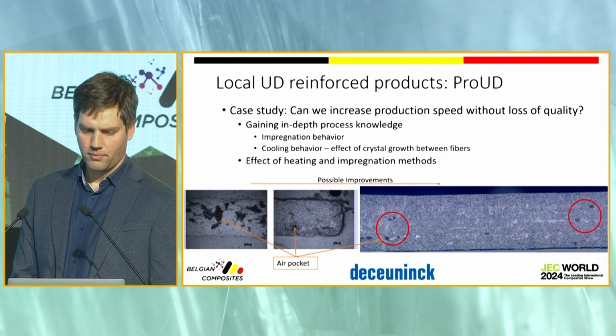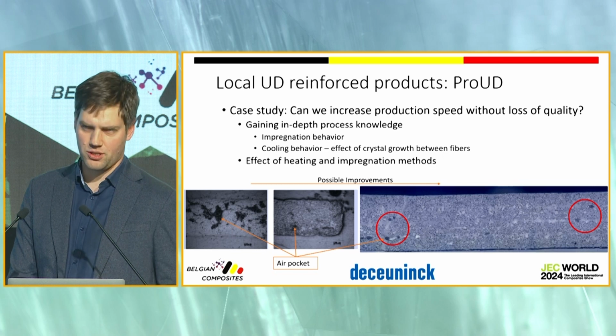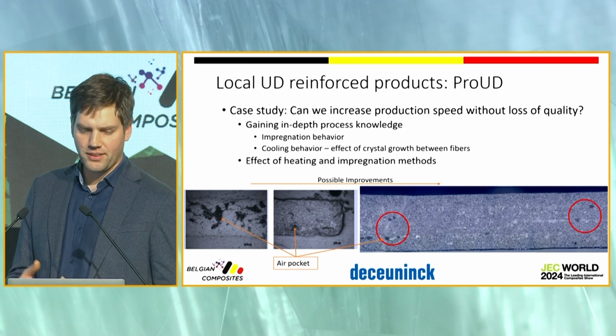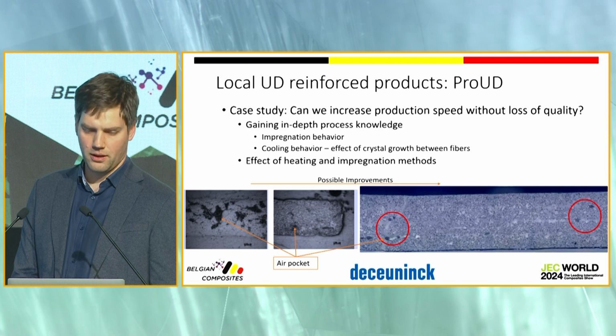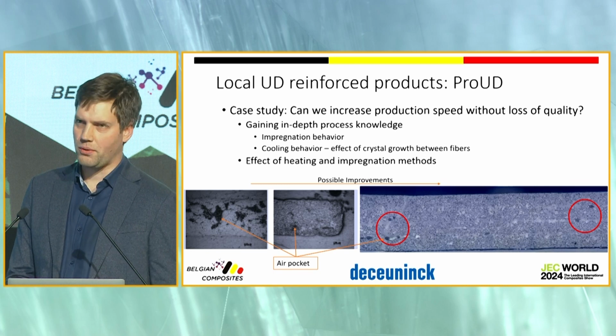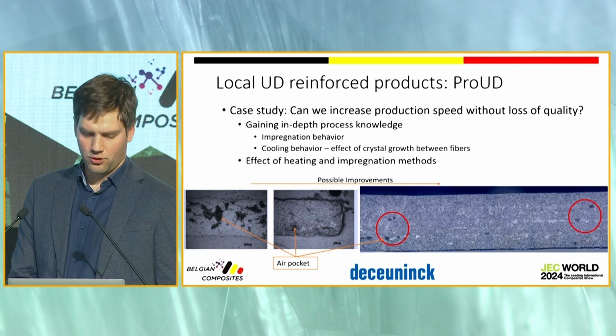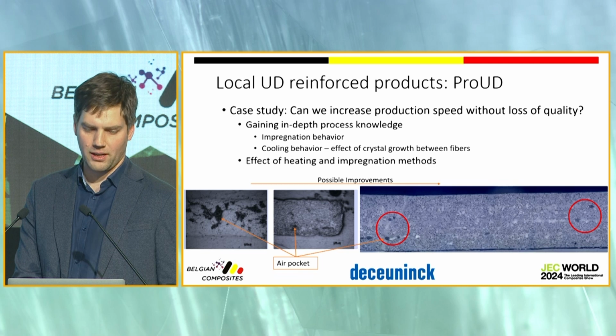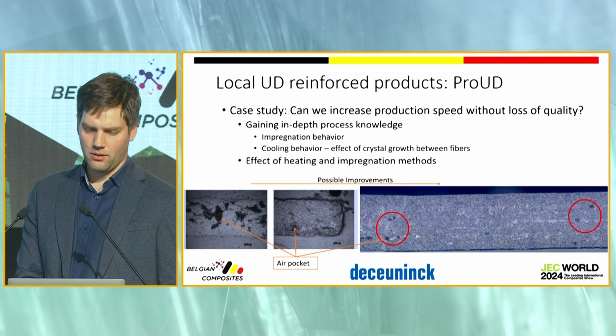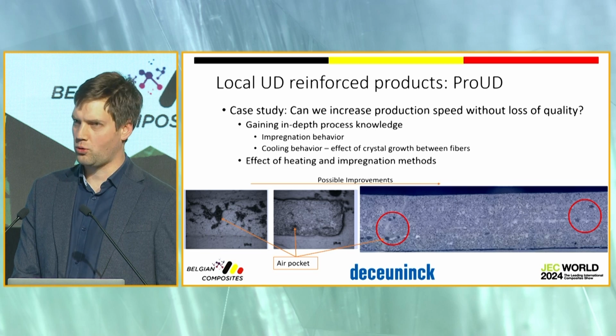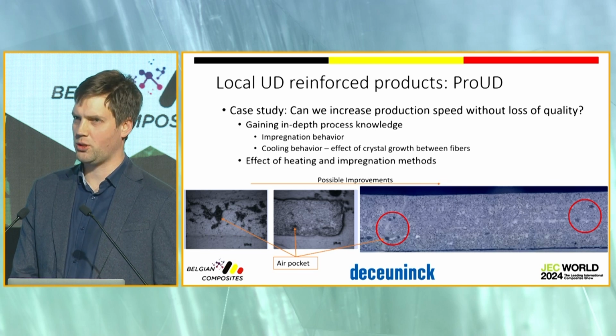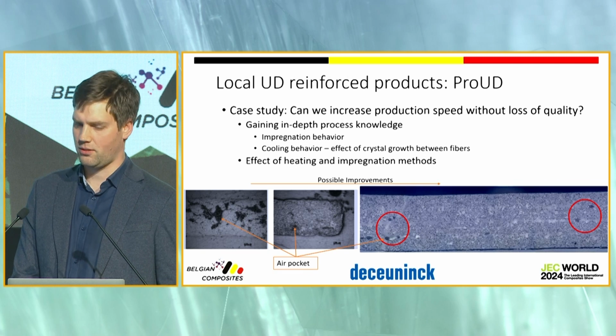So if you look at the case study of the UD reinforcement, we learned a lot during this project on the impregnation behavior and on the process stability we can gain. Here you can, for example, see in the bottom 3 pictures trials we did at pilot scale, showing the effect of temperature, line speed, and impregnation pressure on the air pockets in the glass fiber tape. And of course, we all know air pockets mean low quality. If we do not control the process well enough, we end up with a lot of air pockets. But if we control the process, we can go to almost no air pockets. Zero air pockets is almost impossible in our case, but this limited amount of air pockets is more than enough for us.